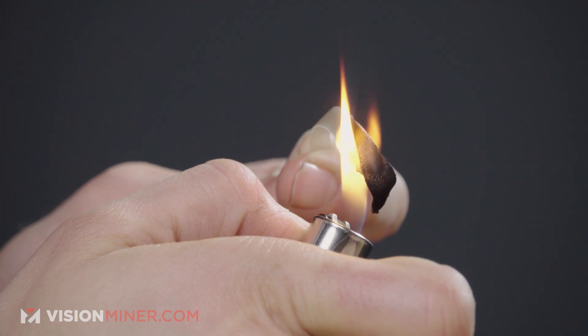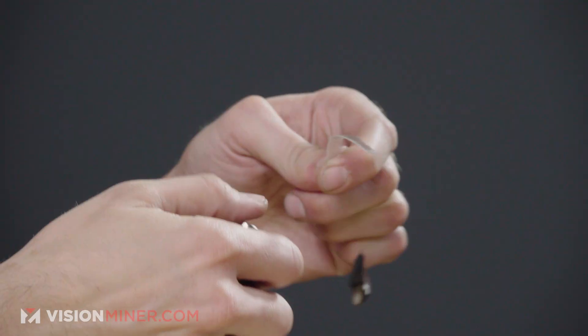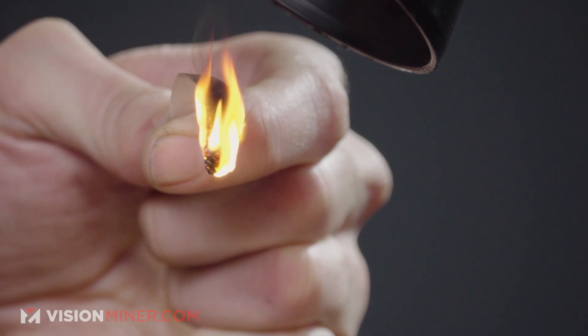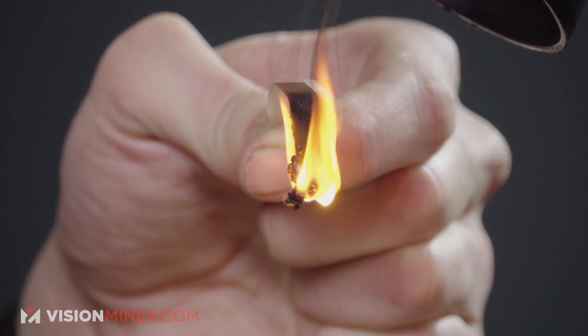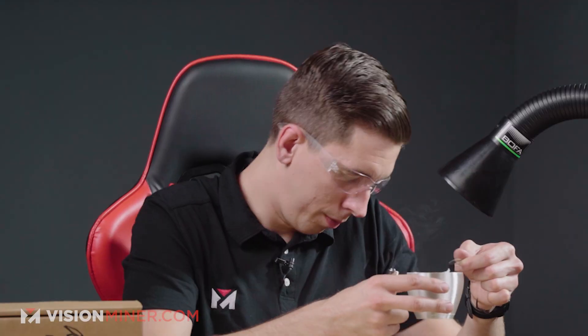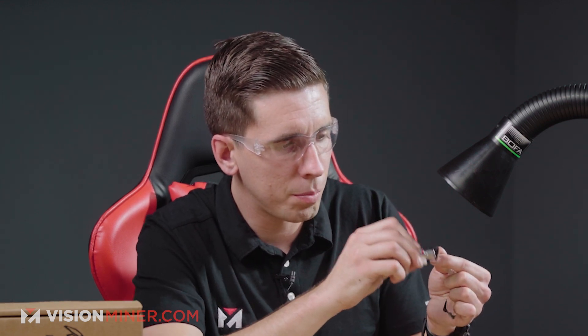Let's get another look. A five-second exposure did not light it on fire — it did smoke a little bit but stopped already. After a longer burn of eight seconds, once it's burning it doesn't go out. It doesn't look like it's dripping in particular — but it did drip once. It's definitely carbonized a little bit and become brittle.